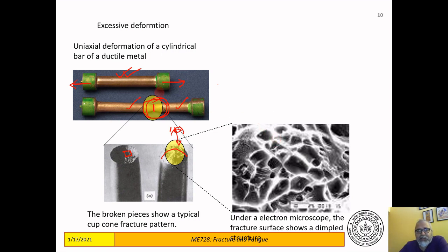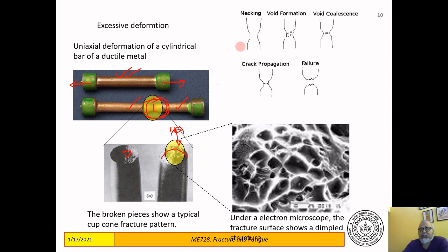People have looked at this. What people have done is taken a dog bone, pulled it to some extent, cut it across and looked at the surface, then taken another one, pulled it some more, cut it, looked at the surface, and doing this they have pieced together how this particular process happens. And this process actually happens along this route. So you have the start of necking, which is an instability phenomenon. You have a start of necking in this region. So you're pulling like this.